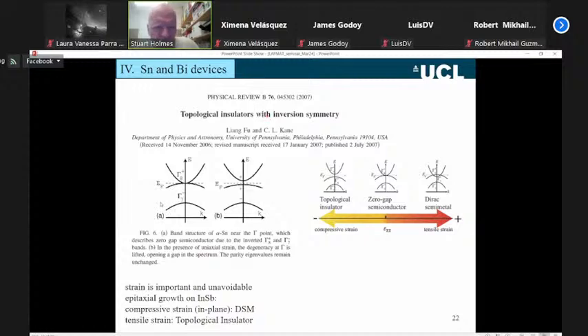Just to quickly show you the band structure in these materials, it's got an inverted band structure. So the top of the conduction band is made of p states, and below that we have the s states. So the bands have kind of crossed over in this material. It's zero band gap. When you add strain to the system, the strain can open up a small band gap. These alpha tin materials are grown on indium antimonide. So it's the same indium antimonide that I've talked about earlier. It's acting as a substrate for the tin, and tin has a slightly different lattice constant. So we can build in a strain into this material.